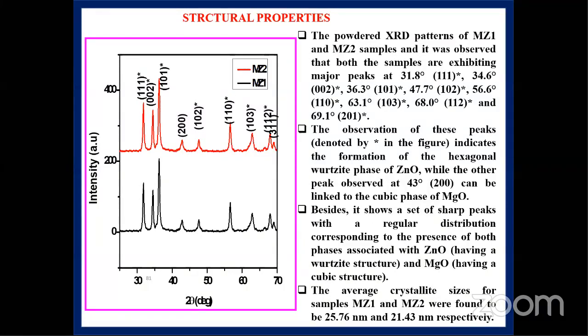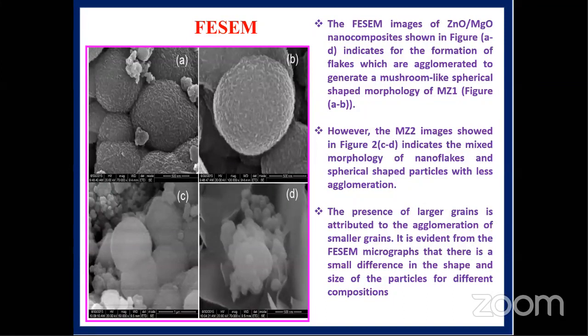And then we calculated the crystal size. You can see the crystal size calculated from the two different ratios of this composite. The crystal size was found to be 25.76 nanometer for MZ1 and 21.43 nanometer for MZ2. You can see that when you change the concentration of the precursor, or change the ratio, the grain size also changes. You can see here 25.76 for MZ1 and 21.43 for MZ2. This is quite interesting.